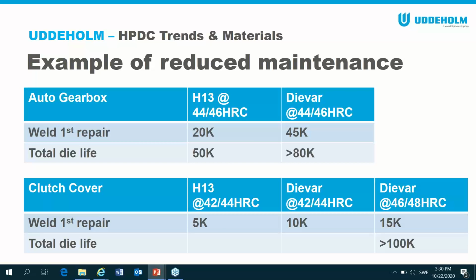Again, some more examples from my travels. The auto gearbox here is from China, near Shanghai, and it's an H13 and they run Dievar as well. They do first weld repair at 20,000 shots with H13, and with Dievar it's 45,000. So you can see a big improvement in the maintenance life of the dies as well, not just total life. The H13 would go on to do 50,000 shots and the Dievar well over 80,000. So again, we see that figure in China of well over 80,000 shots compared to 50, 60,000 for an H13.